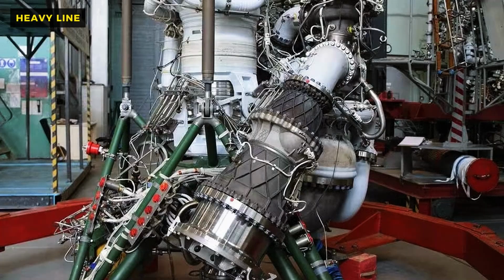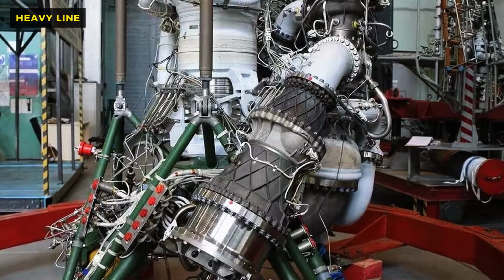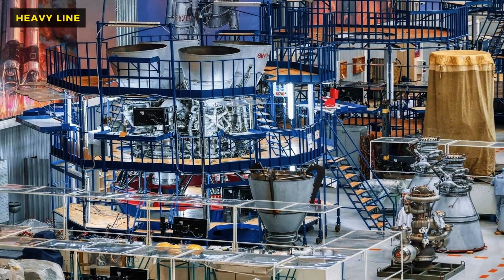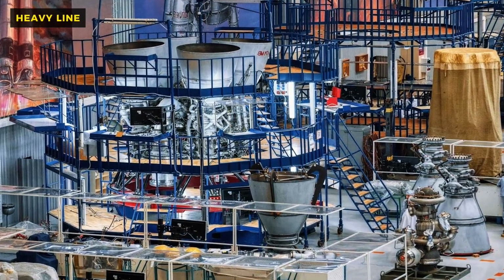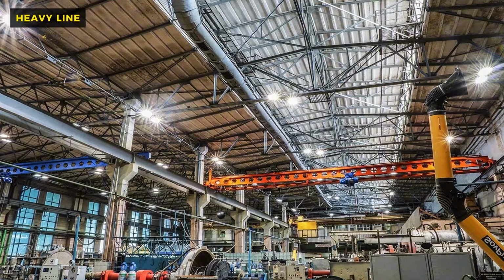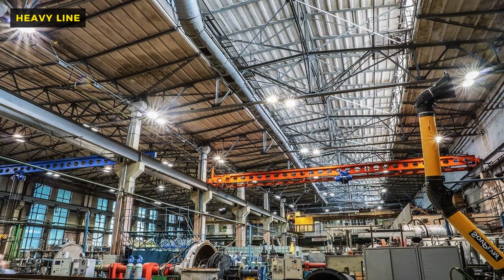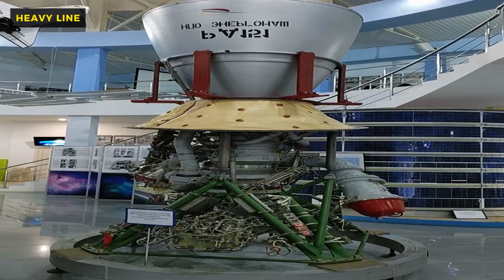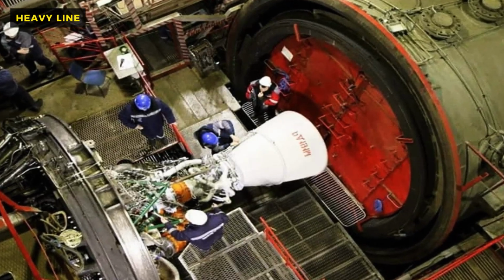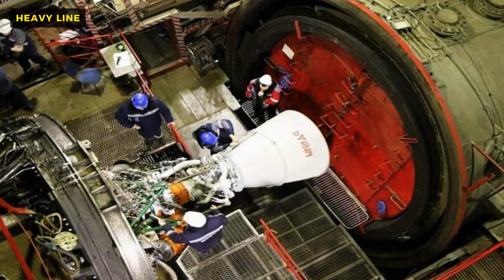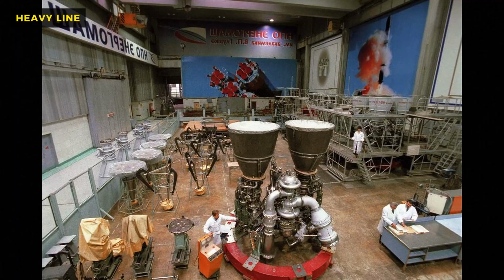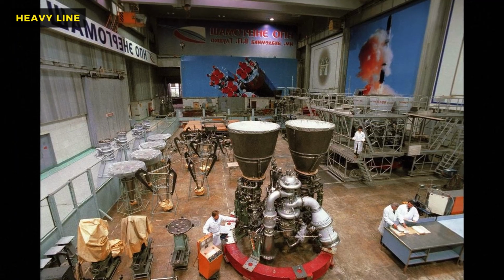The combustion chamber itself is where the final act of this violent ballet takes place. In the RD-170 and RD-180, the fuel and oxidizer meet at pressures that are almost incomprehensible, over 3,700 pounds per square inch. At these pressures, the fluid dynamics change. The propellant doesn't just burn, it behaves more like a detonating explosive that is continuously being fed. The walls of the combustion chamber must survive temperatures that exceed 3,000 degrees Celsius, which is hot enough to boil steel into a vapor. To prevent the engine from melting, Energomash utilizes a technique called regenerative cooling.